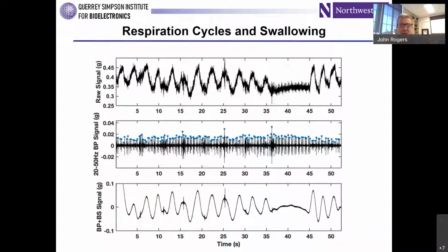You can also, at the same time, as I mentioned before, capture cardiac activity and swallowing. So here's an example of raw data, the top graph, captured from a patient while they're sitting still and they're not speaking. And what you can see is it looks kind of like noisy data, but if you apply digital filtering algorithms, you can separate out the high frequency components, and that's what you're seeing in that middle graph. Those are cardiac sounds, and so you can measure heart rate variability very easily. You get that immediately. You subtract out that high frequency component, and then you're left with the respiratory cycles. You can see these oscillations up and down. That's corresponding to inhalation, exhalation.